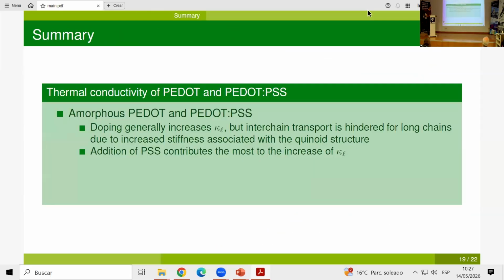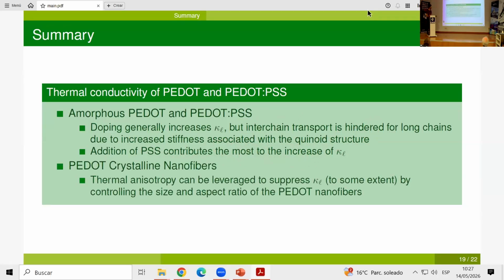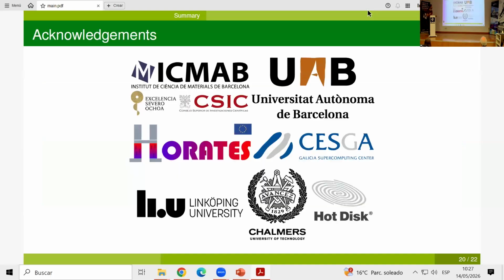So as a summary, we found that doping generally increased the lattice thermal conductivity, but interchain transport is hindered for long chains due to the increased stiffness associated with the quinoid structure, and that the addition of PSS contributes the most to the increase of lattice thermal conductivity. Whereas in this system, the PEDOT crystalline nanofibers, we see that thermal anisotropy can actually be leveraged to suppress lattice thermal conductivity to some extent if we are able to control the aspect ratio of these fibers.